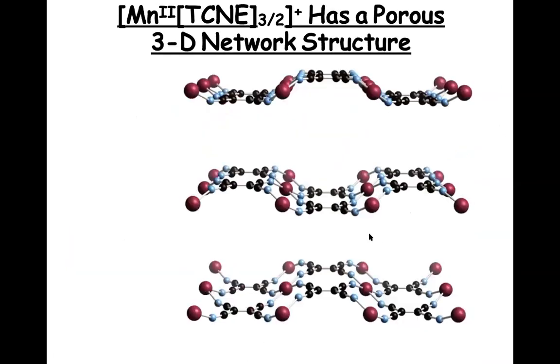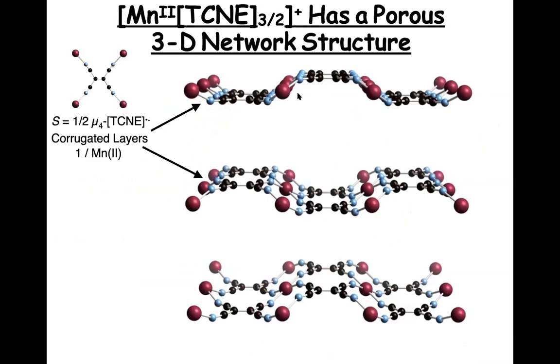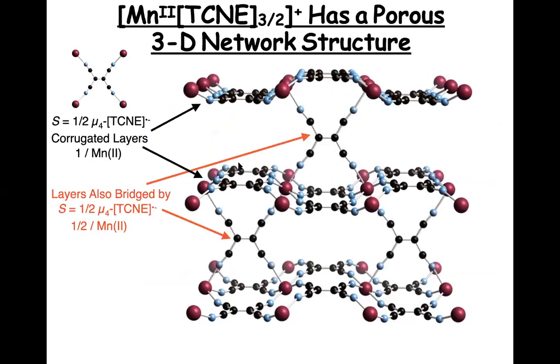And in this case, we see these layered compounds of mu4 TCNE radical anion bridging this layer here. But between the layer, instead of the diamagnetic C4(CN)8, we have a radical anion that provides spin. And when it provides spin, it gives you strong magnetic coupling between the layer above and below, as opposed to weak magnetic coupling, as I showed you in the previous slide.